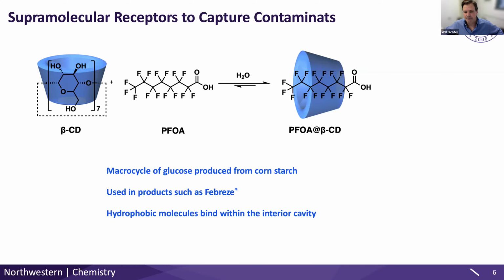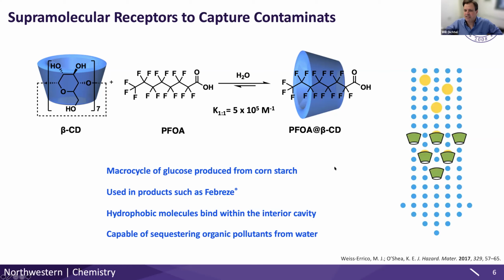And so this is known and even quantified, where we can define the math of how well this process works. And so if you think about this as a reversible process, it favors the right-hand side under particular conditions by a factor of about 10 to the fifth. So very, very good binding site for a molecule like PFOA. And so the idea here is that we'd love to take these cyclodextrin cups, coming from corn, and really, really good way to catch PFOA.